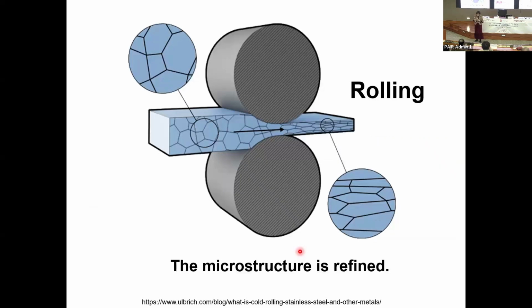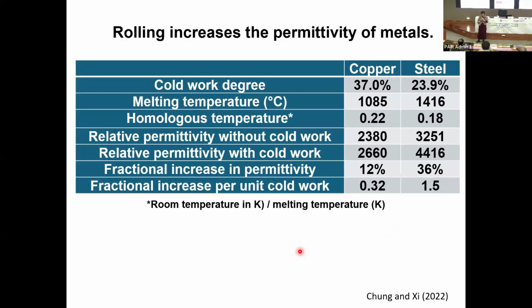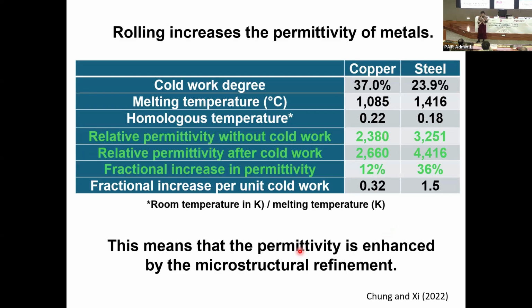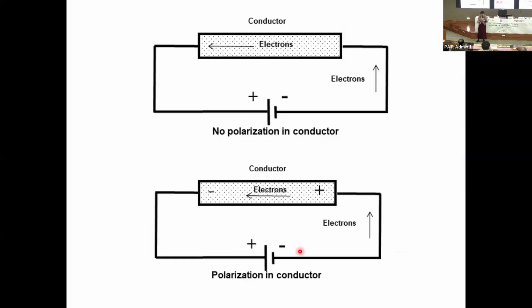Now, one can do rolling, particularly if it's a metal. The carbon, you can't do rolling, but metals, you can do rolling, and the microstructure is refined by the rolling. So we want to look at the effect of rolling on the permittivity of metals, copper and steel, and we find that the permittivity is significantly increased by the rolling, and that is by the microstructural refinement. And so the refining of the microstructure is very important for enhancing the permittivity.